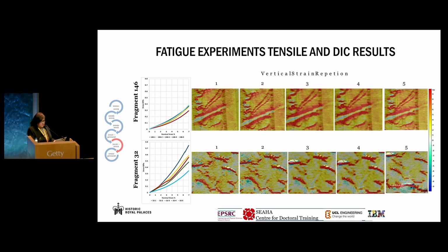So to study the potential impact of fatigue in areas with design changes and stitched slits, 2 historic fragments were tensile tested in the same area. So in the slide, you can see the stress-strain curves until 7% strain for 5 tensile tests on the left and the DIC images on the right. The results from the fragment on the top show little change following 5 vertical strain repetitions. However, for fragment 32, which is at the bottom, the stress-strain curves become consequently less stiff, as the DIC map shows increased strain in areas where the stitched slits become more loose and open up. So again, quite interesting information about the behavior that our tapestries experience when they're under strain from their weight.